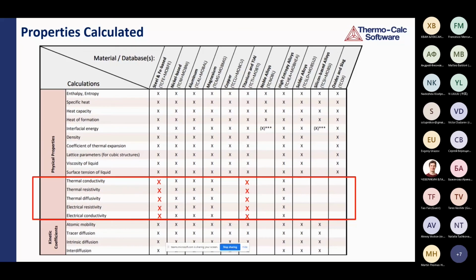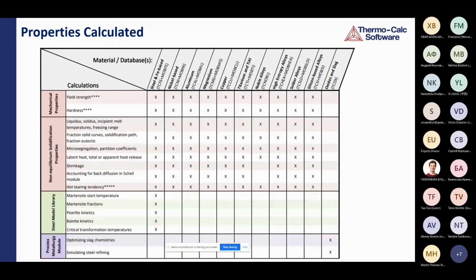And we also have physical properties, and that could be like enthalpies and interface energies and so on. But lately we have also worked a lot with thermal conductivity, resistivity, diffusivity, and electrical resistivity and conductivity, for example, and also viscosity of liquid and surface tension of liquid. And today we actually have them for most of our bigger databases. It could also be kinetic coefficients, for example. Other properties could be mechanical properties, yield strength and hardness. It could also be non-equilibrium solidification properties. That could be very important for additive manufacturing, for example.